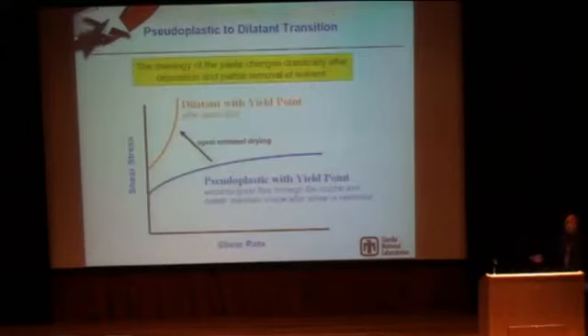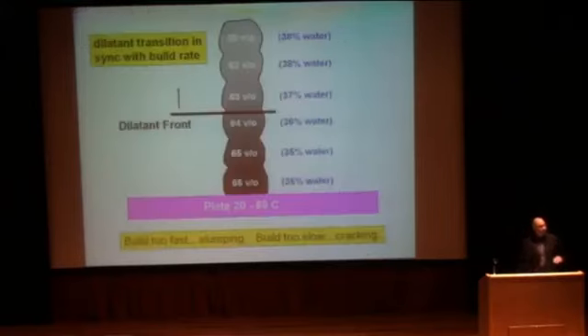From a rheological standpoint, what you're looking at in a shear stress versus shear rate curve is that in the tube, you're in a pseudoplastic state with a yield point, and with just a little bit of drying you transition to a dilatant state, where the more stress you put on it, the more the material is going to resist movement. If you keep this pseudoplastic to dilating transition in sync as you're building, this is a cross-section of a wall you build. If you keep that dilating transition in sync with what you're building, then this becomes a strong enough platform that you can build more on top of it.